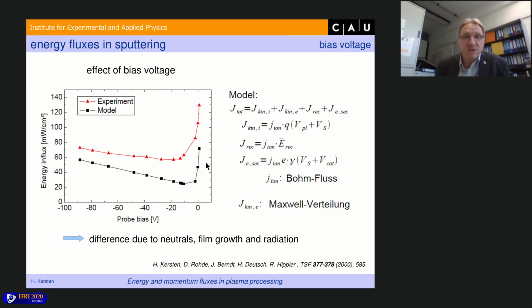And here on the positive branch at plasma potential or positive, there is a steep increase in energy influx. This is due to the electron flux, the flux of the electrons from the plasma. So it is a kind of an additional electrode now, which is a steep heating. The red curve is the experimentally measured curve, and the black curve is the model.